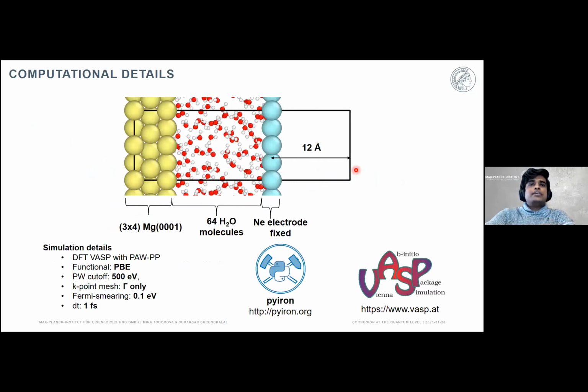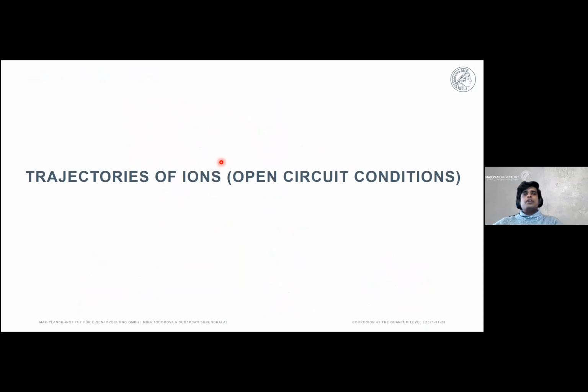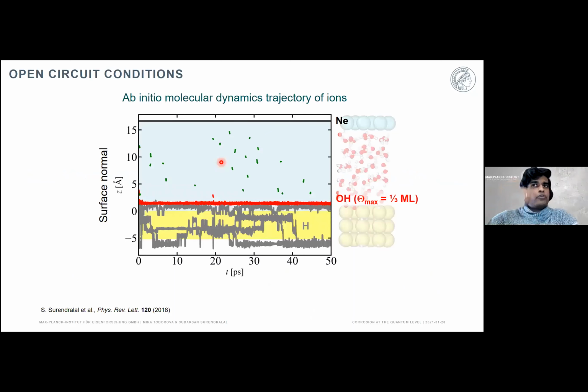In order to do this, we take the setup that I described earlier. We take a 3x4 layer of a magnesium 001 close-packed surface, and we place a certain layer of water molecules on top of it, and then confine it with the neon electrode, as mentioned earlier, in order to apply potential. And then we perform our DFT-MD calculations to see what's going on. So what I'm about to show you is the results from our density functional theory molecular dynamics calculations, where we track the trajectories of the ions in our simulation. We don't track the trajectories of the water molecules that are intact, but only those of the ions that are there.